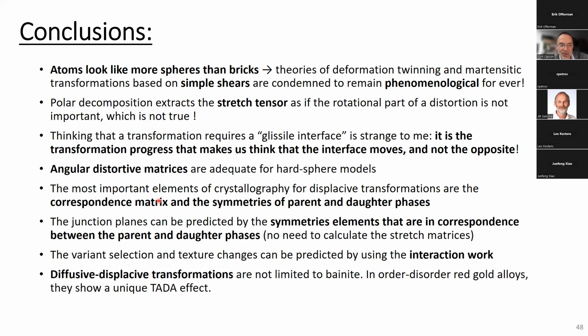I skipped that part, but I wanted to stress that the correspondence matrix and the symmetries of the parent phase and daughter phase are very important. What I wanted to show you is that it's possible to calculate the junction planes just by using the correspondence matrices, exactly as Bevis and Crocker did for deformation twinning. We could do the same for transformation twins. We do not need the long and complex PTMC calculation to do that. But if you are interested, please contact me. And we can predict variant selection and the change of texture by using the interaction work.